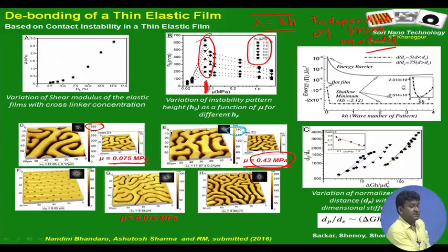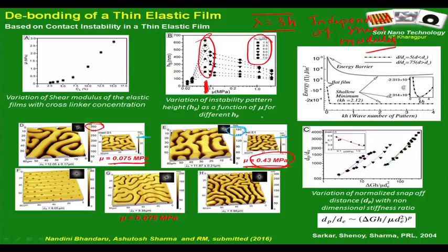And in both the cases you see that in these very carefully performed experiments, the initial contact is established when the separation distance is of the order of 60 to 70 nanometer. So, this is in fact a very direct validation that these van der Waals forces between two surfaces stretch up to about 100 nanometer, maybe slightly less than that.